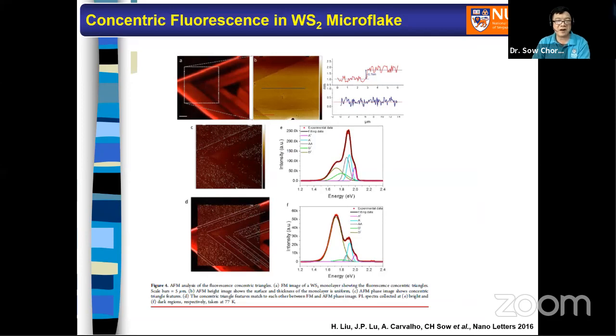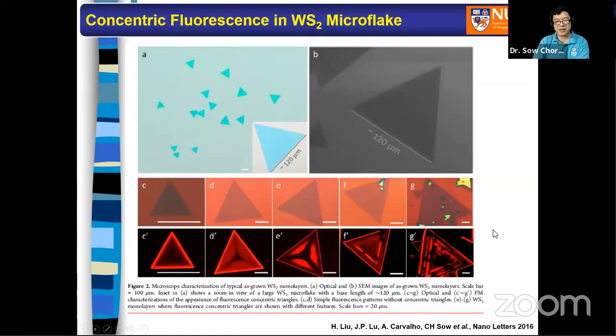Different deficiency in sulfur gives rise to a different intensity of the fluorescence, and more than that, a different nature of the exciton, because the exciton species in this system is very complex, consisting of neutral exciton, bi-exciton, trion, defect-bound exciton, and so on and so forth. Okay, so a simple system like this, just by looking at the detailed chemical stoichiometry distribution, allows you to have a very beautiful fluorescence concentric pattern in this way.